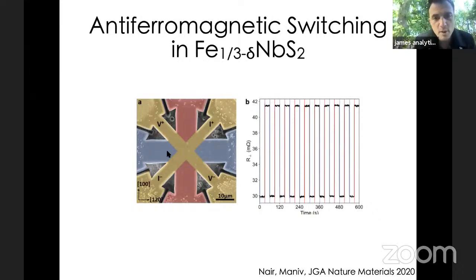So now we have the blue pulses in the east-west and the red pulses in the north-south, and you get the same kind of switching from up and down, just like you would expect: high resistance, low resistance. In other words, it seemed to work in this material as well. The material breaks inversion symmetry, it has antiferromagnetic order, and it seems to go from this high resistance to low resistance state when you apply these current pulses.